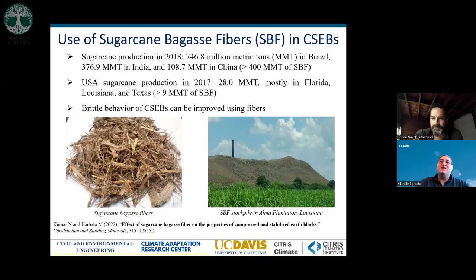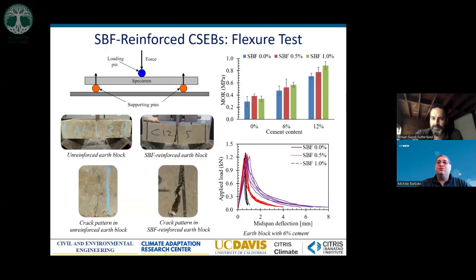And so we have these 28 million tons of sugar cane that are produced in Florida, Louisiana, and Texas, which lead to more than 9 million tons of sugarcane bagasse fibers that need to be disposed of every year. And we are trying to find a use for that. And so what we did, we considered blocks with three different amounts of cement, 0, 6, and 12%, again expressed as weight of total solids. And with three different levels of sugarcane bagasse fibers, 0%, 0.5%, and 1%. This amount is expressed in volume of the material.